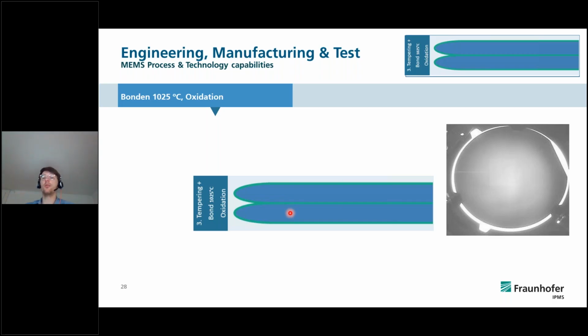And what you see here on the right side is an IR measurement, or an IR camera shining through the wafer to see whether there are air bubbles or particles bonded in. And as you can see here, there are basically no residuals, particles, or anything that interferes with the bonding of those wafers.